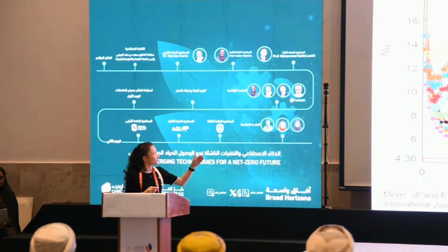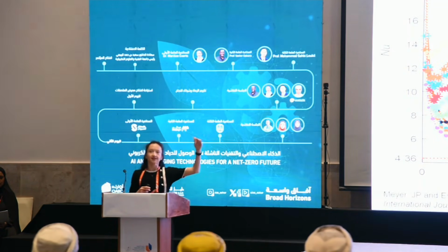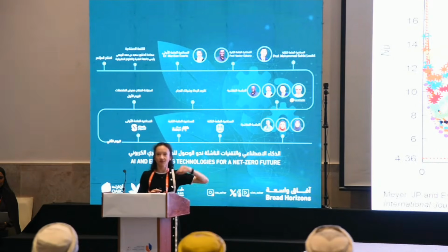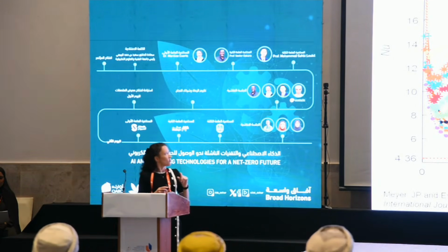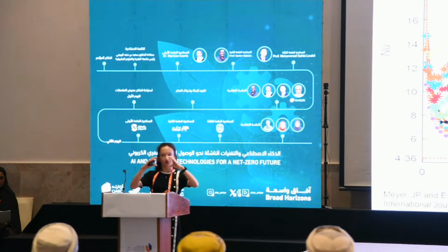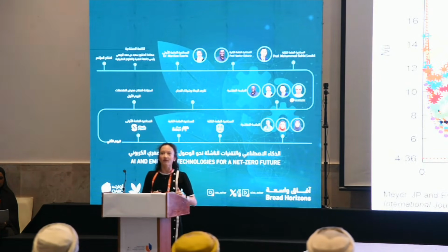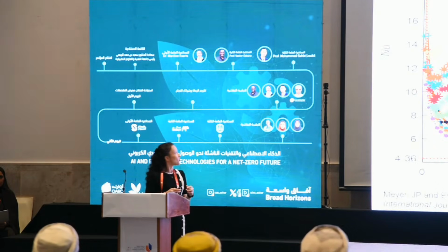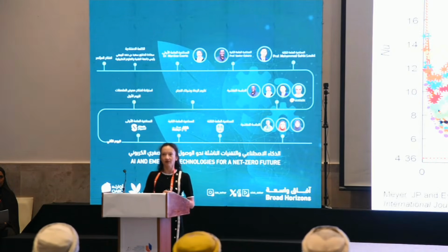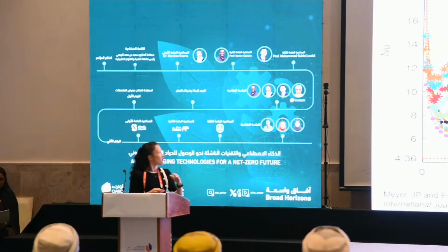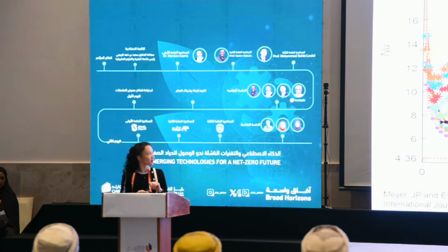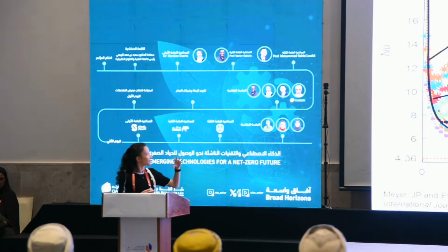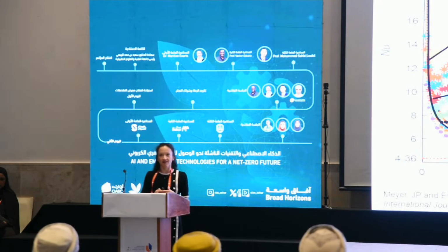So as we expected, an increase in diameter led to increased heat transfer coefficients. But then also, if we look at a specific group, for example the 11.5 millimeter results, we see that as we increase the heat flux, again, we increased the heat transfer coefficients, which is what we expected. But when we look closely at the trends in these graphs, distinct regions and behavior were identified,